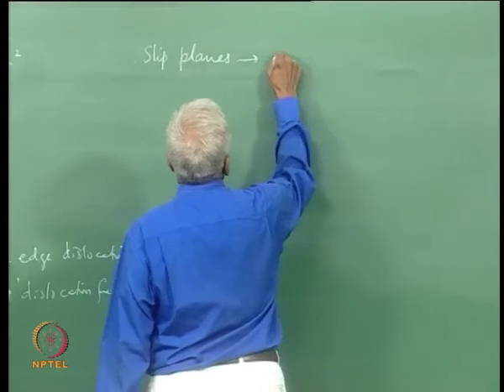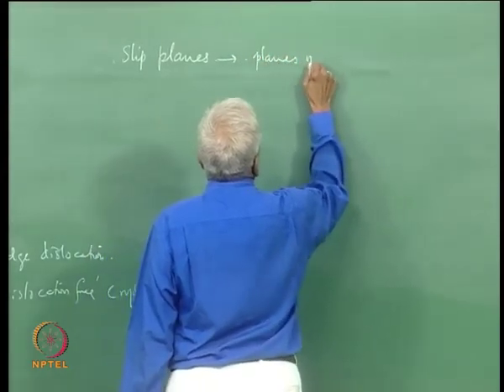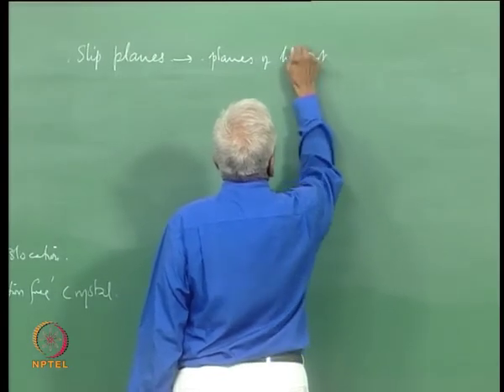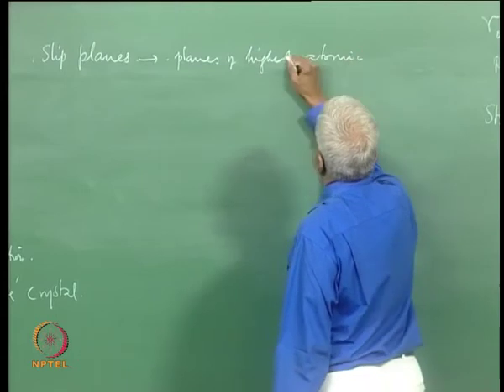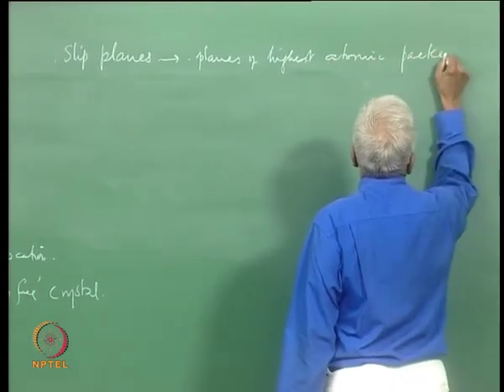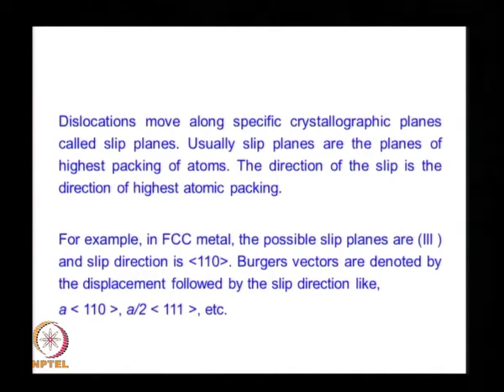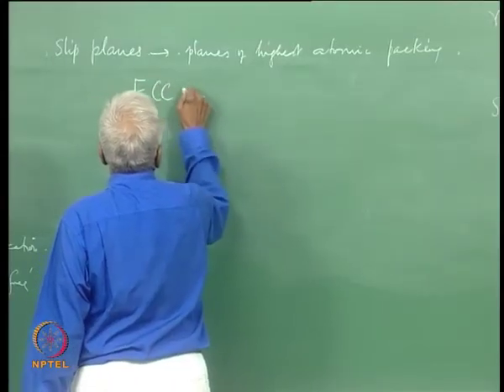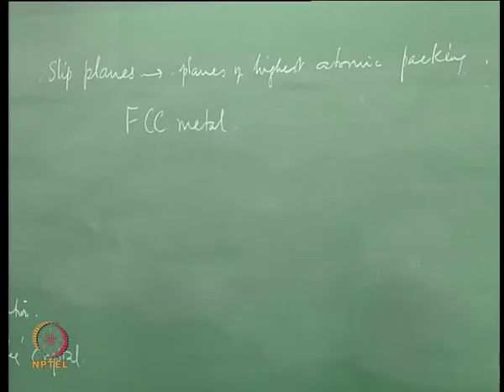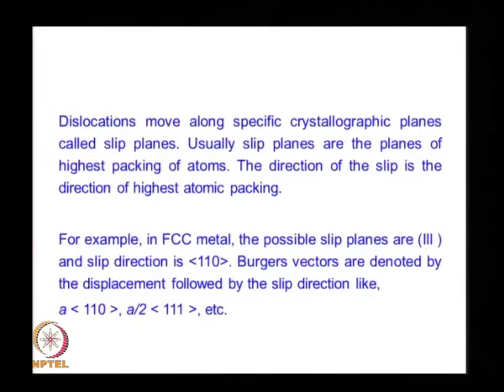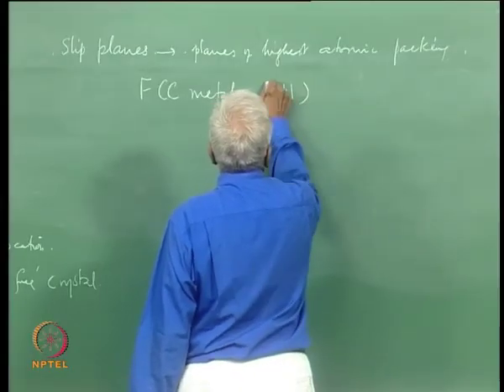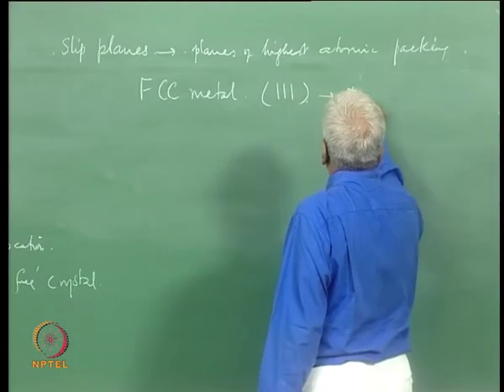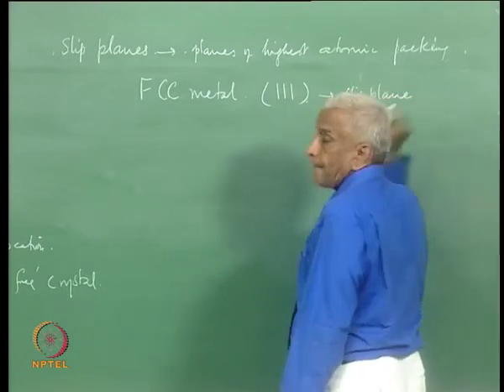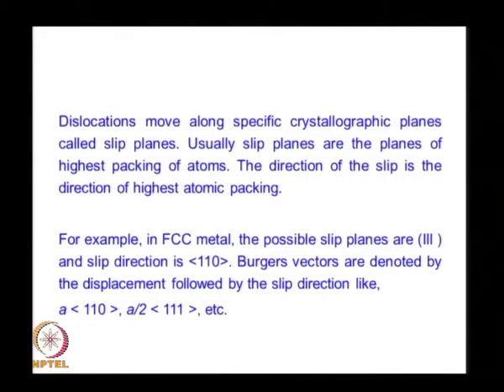Usually, these slip planes are planes of highest atomic packing. So, the atomic density is highest. So, the direction of the slip is the direction of the highest atomic packing. For example, if you have an FCC metal, then the possible slip planes are {111}, and the slip direction is <110>.